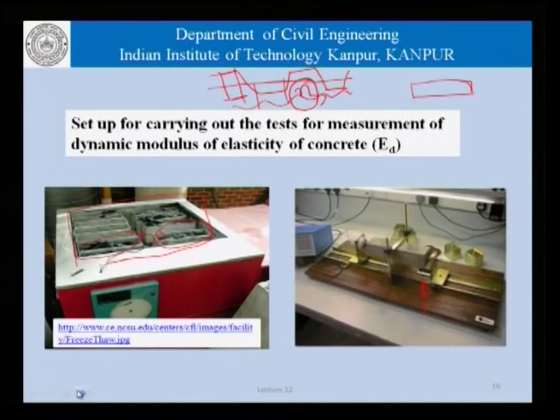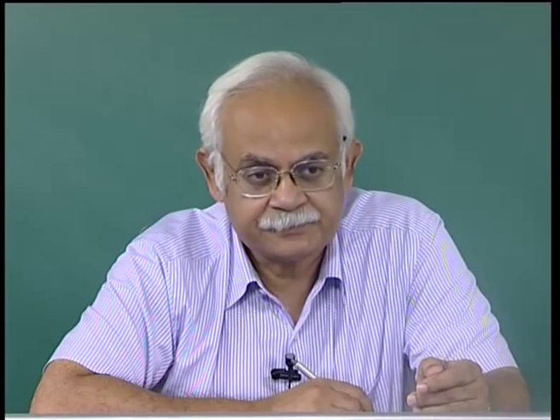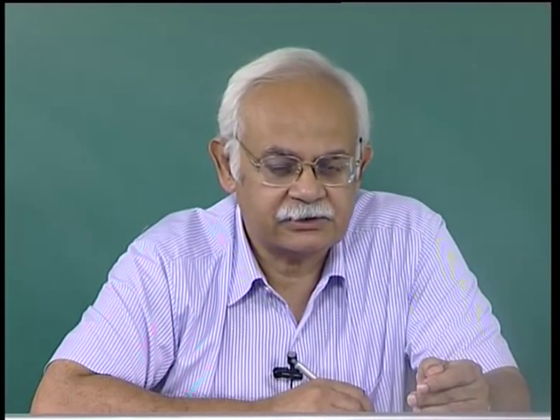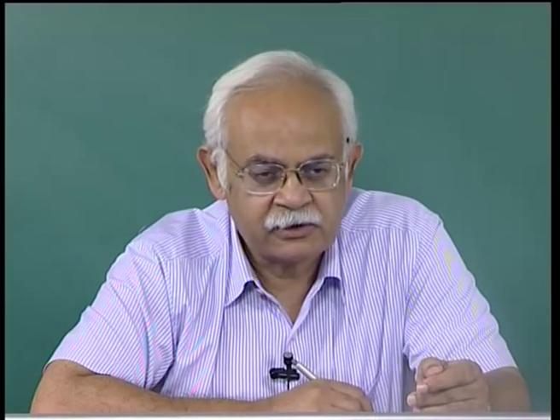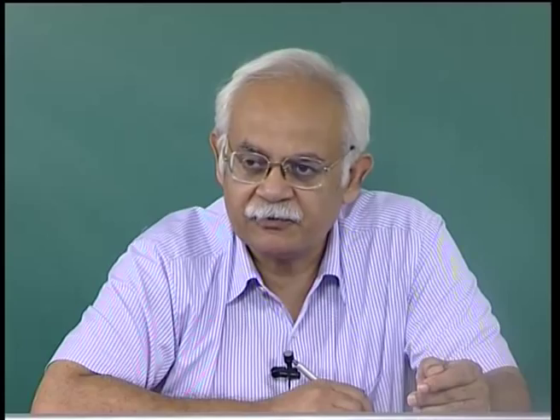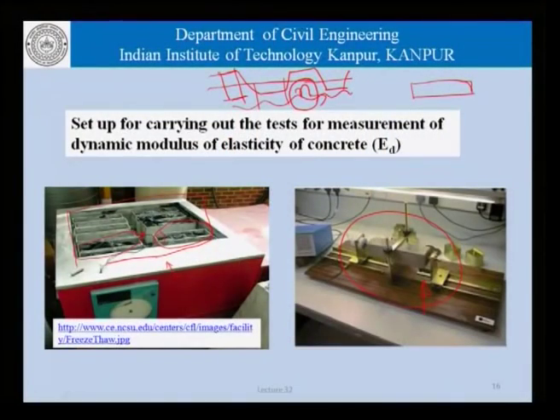If we go back to this setup here, the underlying assumption is that testing the concrete using this kind of a vibrational method does not alter the specimen at all, and therefore, the same specimen continues to be exposed for further cycles in this chamber, and the same specimen can be used at different points in time to see or monitor the changes that occur in the dynamic modulus of elasticity. And that is a very big advantage when using this method, because we are really using the same specimen. It is one of the reasons because of which we also work with the relative values rather than the absolute